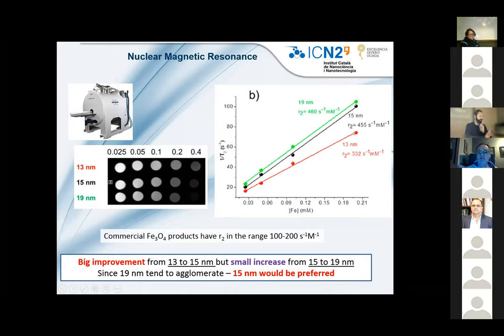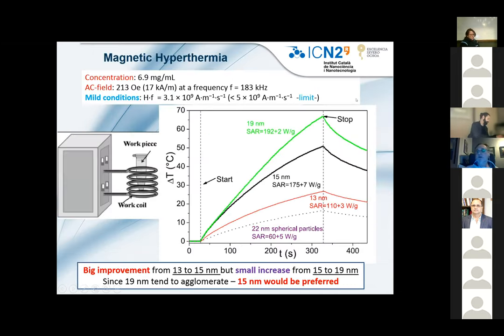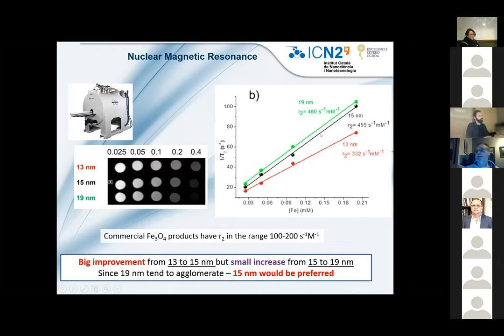So just going from 13 to 15, we get a big improvement in the NMR properties, but increasing further to 19 does not improve the properties. I wanted to mention that commercial Fe3O4 products have R2 values in the range of 100 to 200, meaning that we have more than double the commercial properties. So as I said, we have a big improvement from 13 to 15, but just a small increase from 15 to 19 nanometers. Since the 19 nanometer particles tend to agglomerate, we would prefer 15 nanometers for biomedical applications.